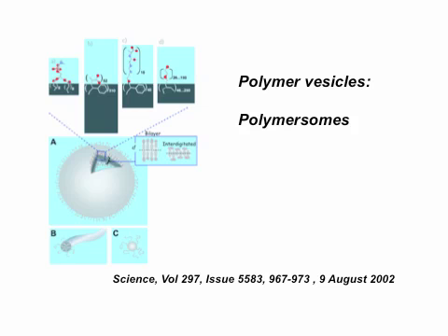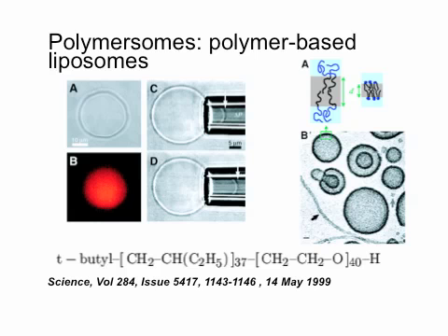An ordinary vesicle typically will have a membrane thickness of 1, 2, maybe 3 nanometers. You can puncture that pretty quickly. If you make it 30, 40, 50 nanometers, these things are a little bit more robust, and that could be quite an interesting object to play with.